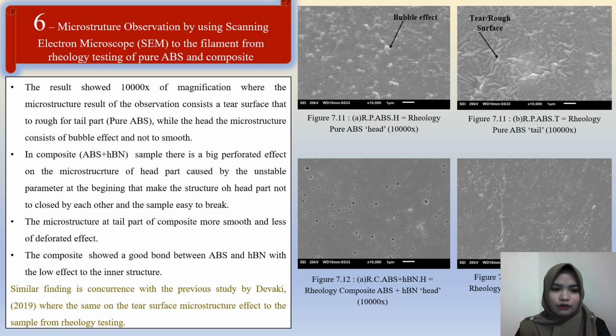In the composite ABS HBN sample, there is a big perforated effect on the microstructure of the head part, caused by unstable parameters at the beginning, which makes the structure of the head part not too close together and the sample easy to break. The microstructure at the tail part of the composite is smoother with less perforated effect. The composite shows a good bond between ABS and HBN with low effect on the inner structure. This finding is consistent with the previous study by Devaki 2019, where the same tear surface microstructure effect appeared in samples from the rheology testing.